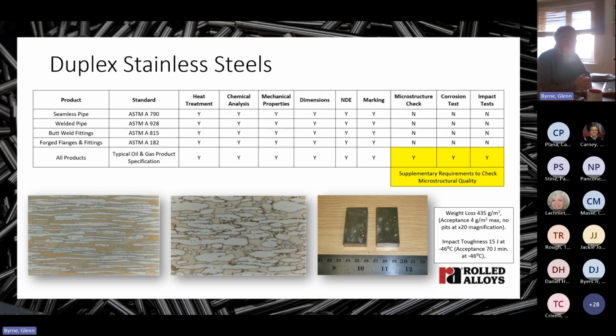But if something goes wrong in manufacture, third phases can be formed in the microstructure. And if you look at this picture here, these dark particles that you see are the third phases that I'm referring to. They're called intermetallic particles, of which sigma phase is the most common. And these particles destroy both corrosion resistance and toughness.